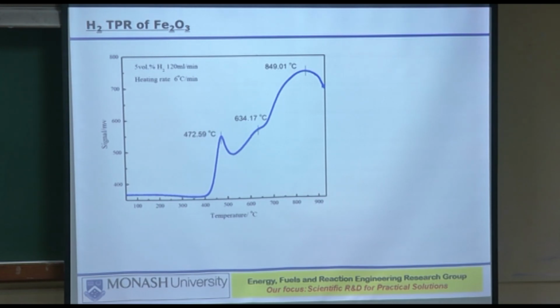Even though we used the same amount of hydrogen, this is research. Not every technique will give you exactly the same answer, but they will give you complementary answers from which you can make a holistic judgment. But that's not all. At one temperature this transformation takes place, at another slightly higher temperature another transformation takes place, and around the 850 degree mark another one takes place. The student then figured out that these correspond to the reduction from Fe2O3 to Fe3O4, then to FeO, and the next one to metallic iron, Fe0.